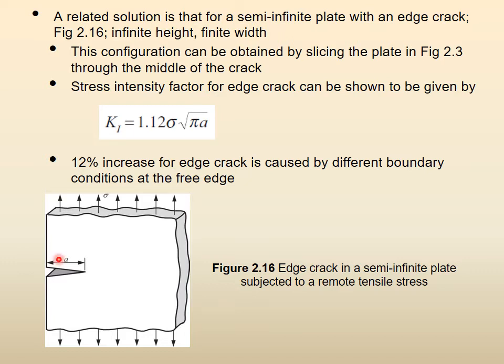Now it is an edge crack, so y has become 1.12. The rest is exactly the same still. So 12% increase in there because of the boundary condition problem, basically. You see, the previous one was totally infinite plate. On the other side also, the edge of the plate was sort of an infinite distance compared to the crack size. This time, on one side, the edge condition is directly here.